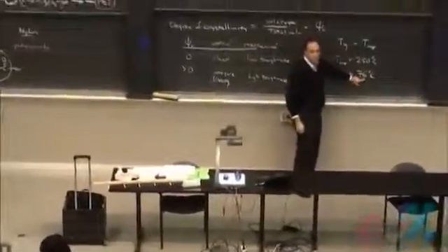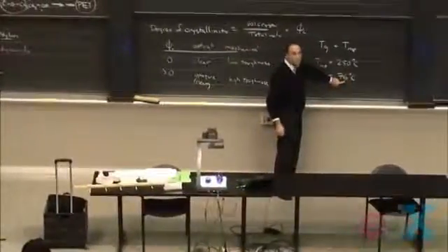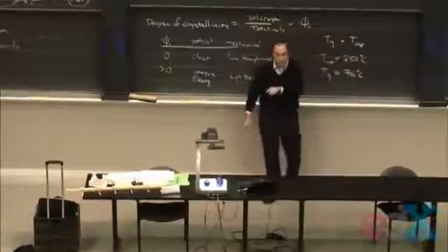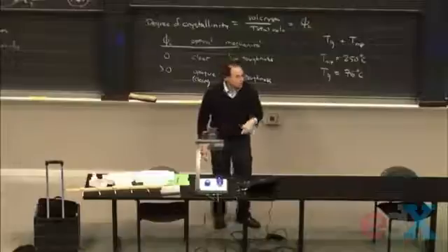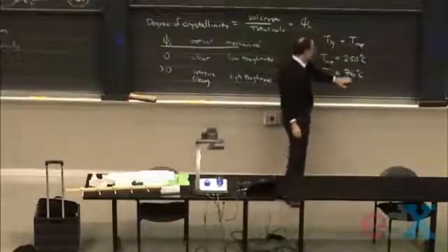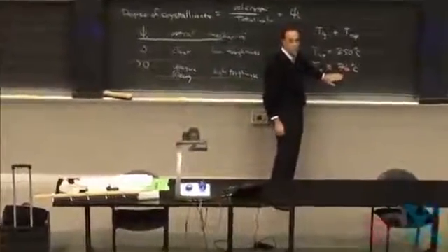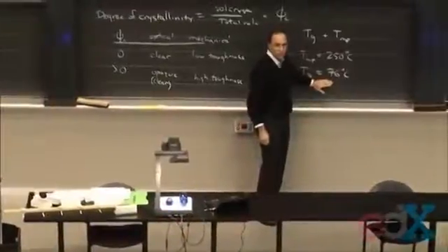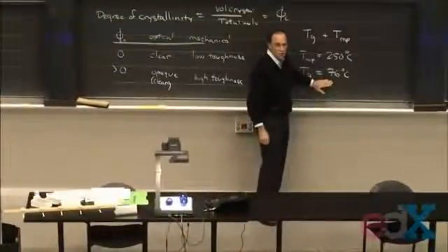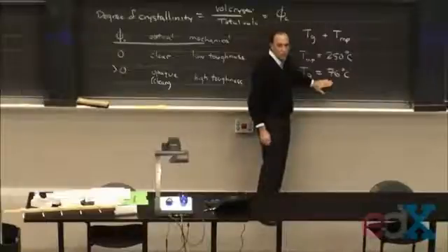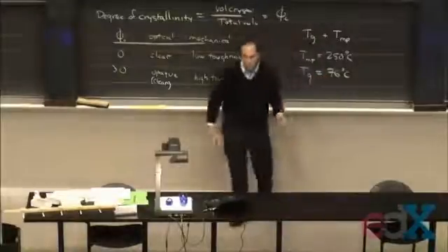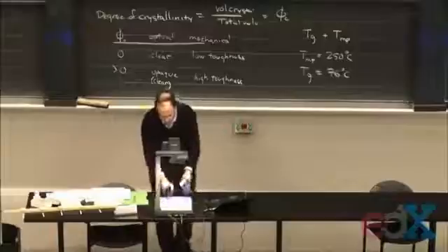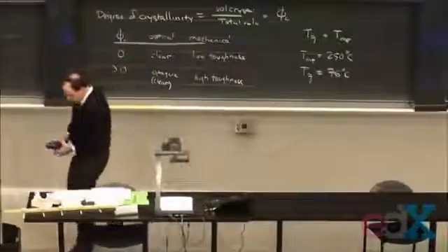Well, I went above the Tg. Didn't melt it. But if this bottle has a high fraction of amorphous material, you know, it's probably close, and especially in my dishwasher, it's up there close to 95 degrees C. It's kind of a sterilizing environment. And the viscosity, of course, starts being a liquid, right? And it's going to start to flow. And that's what we mean by dishwasher safe. Not dishwasher safe.